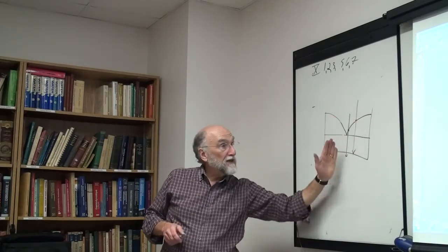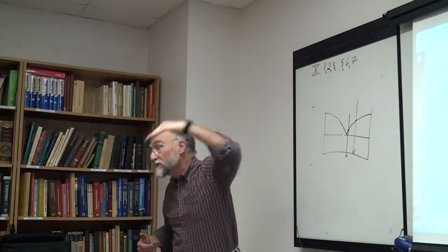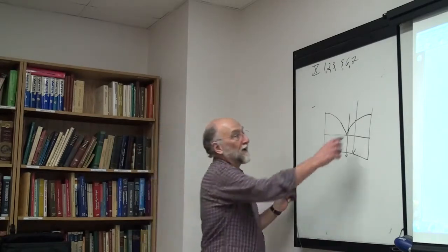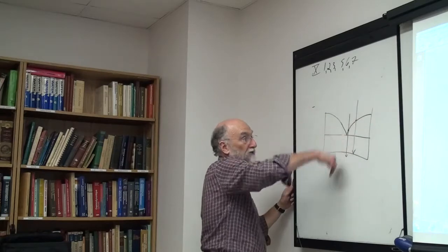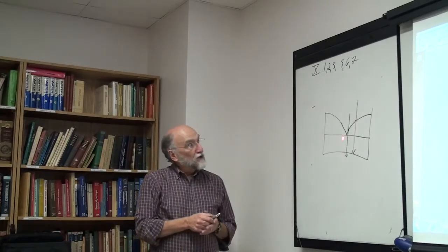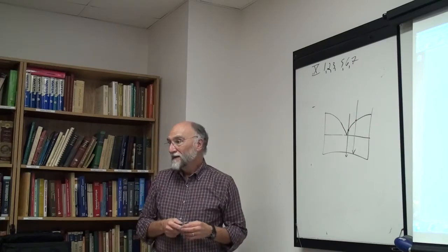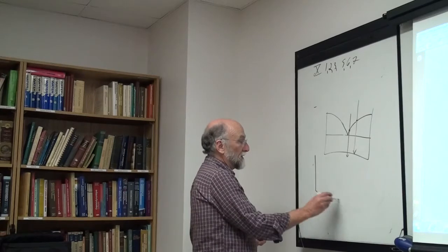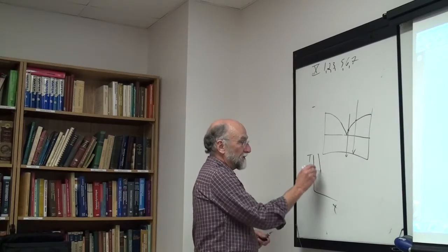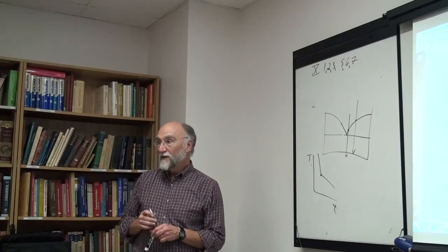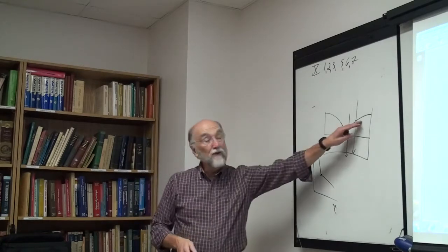As you get down to the eutectic, the liquidus generally tends to be more vertical. So the liquidus up here is quite flat, and down here it's dropping very rapidly. Which is going to be easier to measure, this point or this point, and why? By the cooling curve, remember, you're going to see the change of slope. The temperature-time curve is going to go like this. You want to see that change of slope, so which is going to be the hardest? This one will be easier.